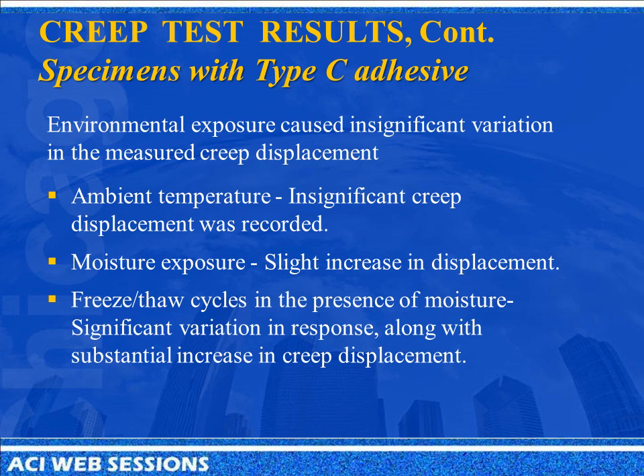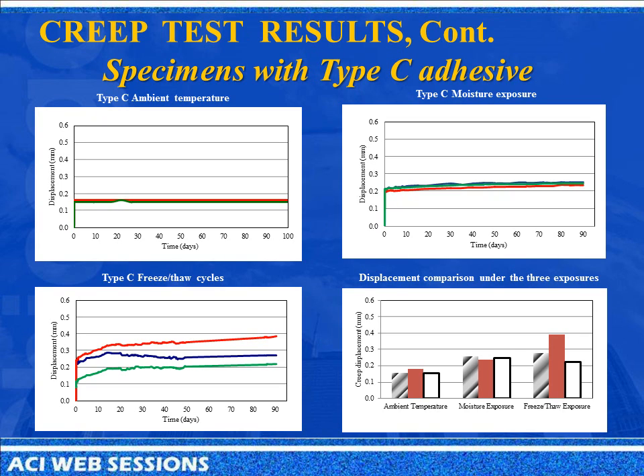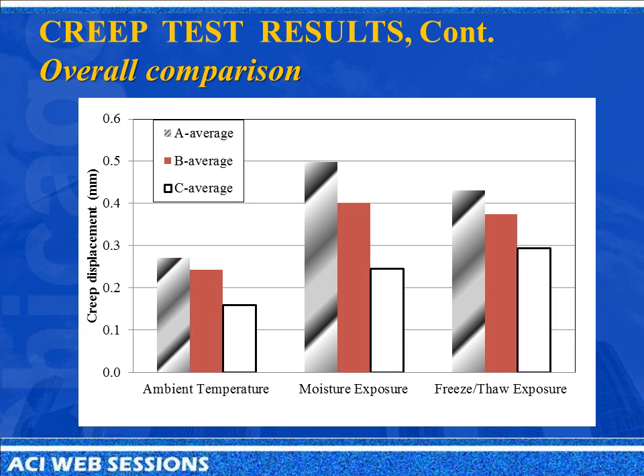So like I said, in ambient temperature, almost no creep is recorded over a period of 100 days. Moisture slightly increased, and with freeze-thaw, inconsistencies are noticed. And again, the bar charts can visualize the effect of the moisture, the environmental exposures. This figure here is basically comparing the average of each adhesive type over a certain exposure.